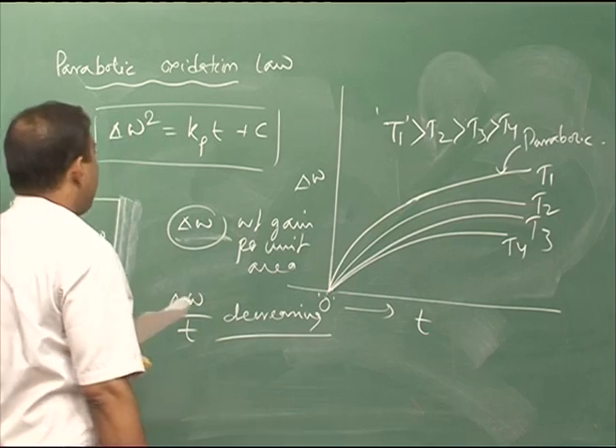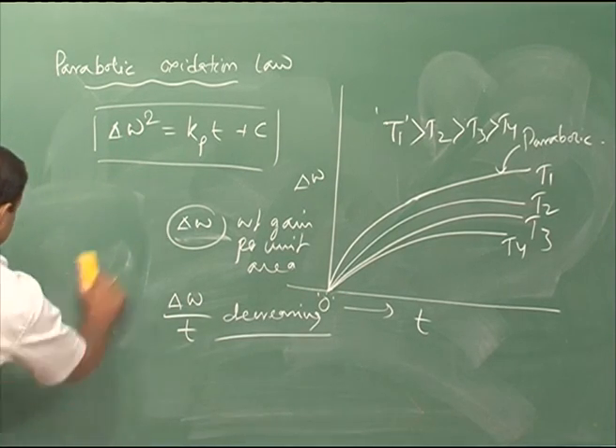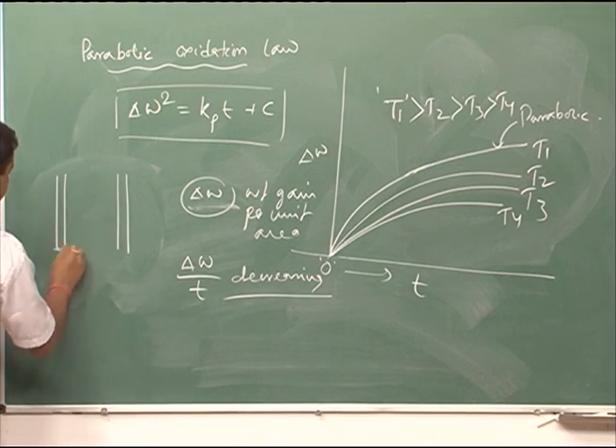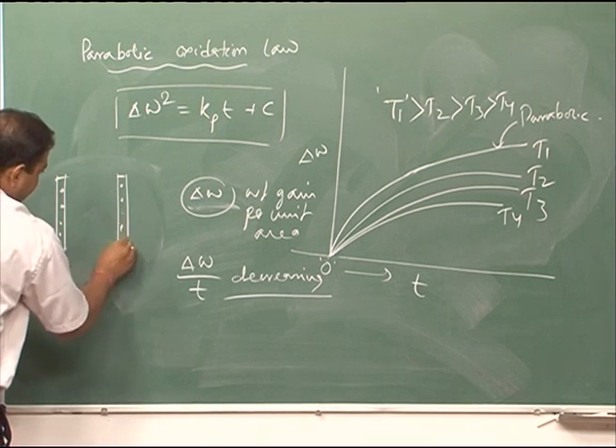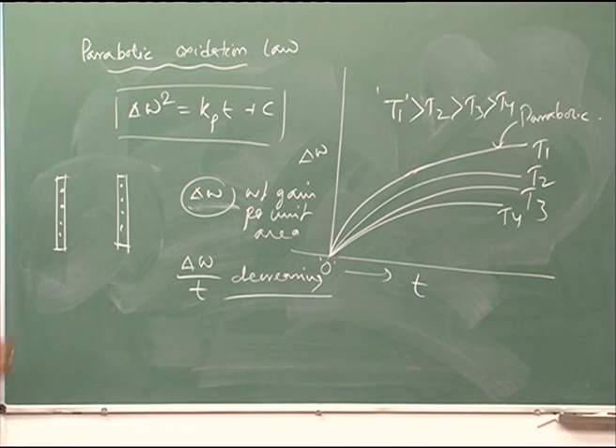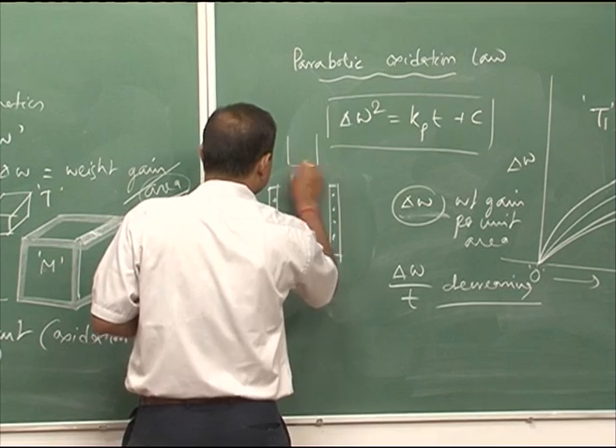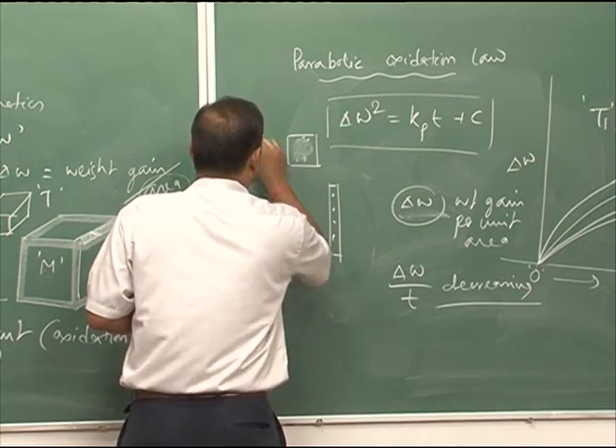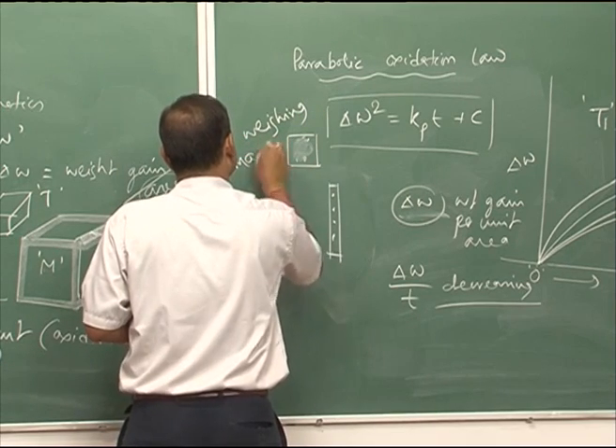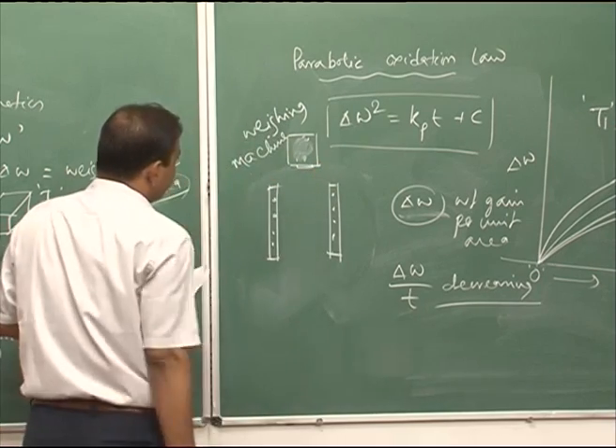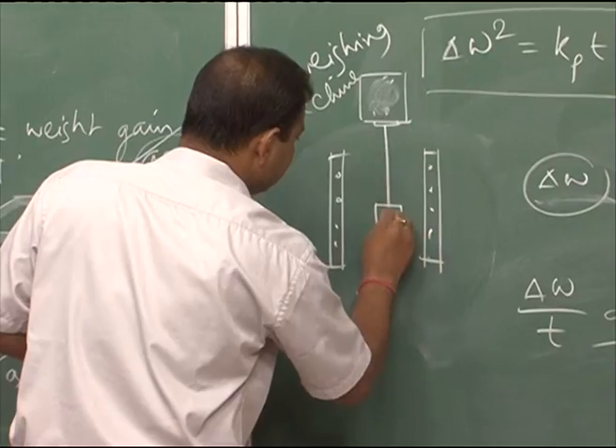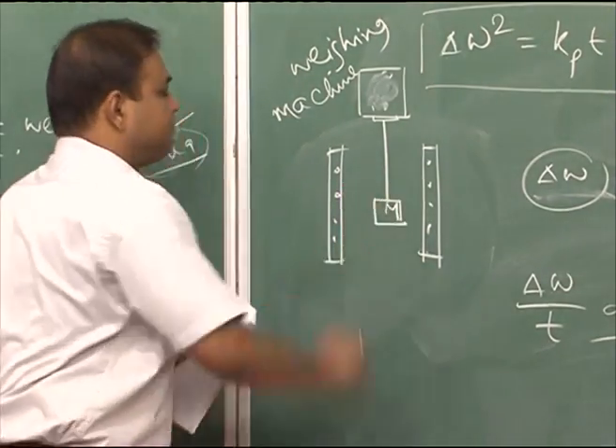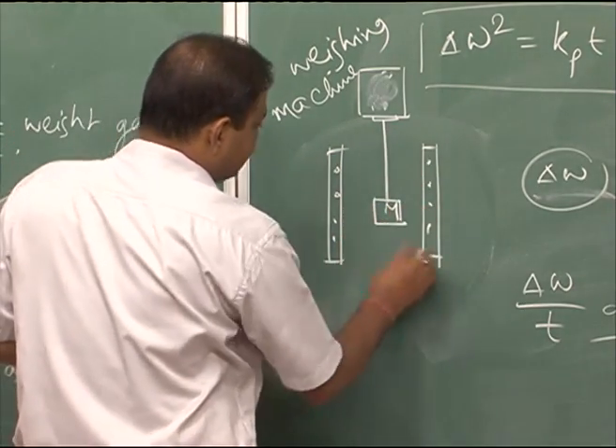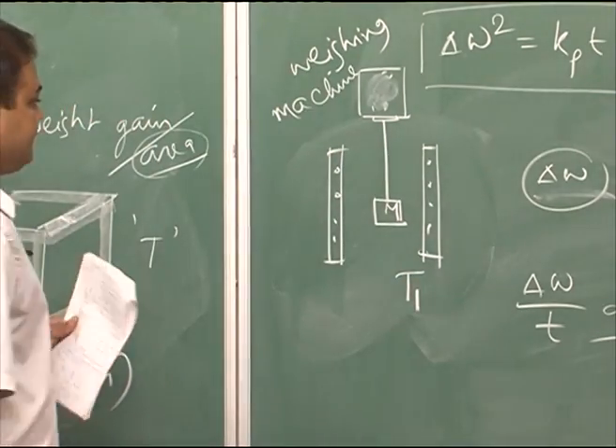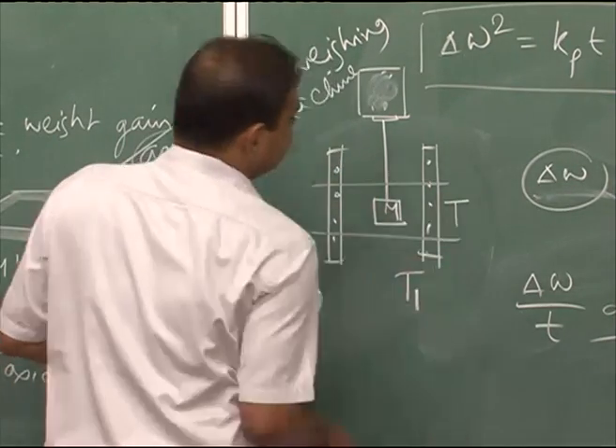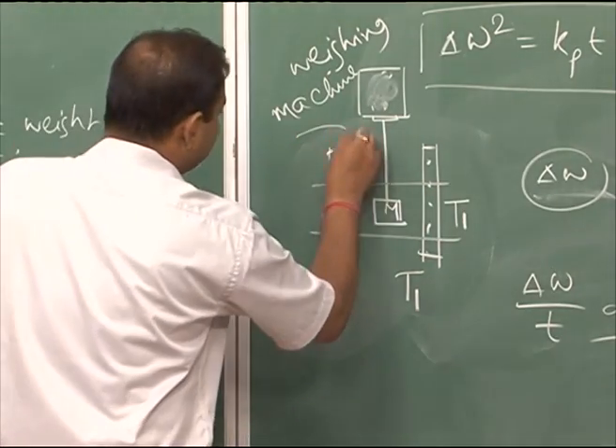How do we do that? Let us say I have one furnace, a vertical furnace, and these are my coils which heat up the furnace. Now, you have a weighing machine, this is the weighing machine WM, and here we have the bottom weighing facility, and from that I will put a sample of metal. This is my metal sample in the constant temperature zone of the furnace. Once the furnace temperature is taken to, let us say, T1, the temperature in this constant temperature zone is maintained at T1, and we can measure that with a thermocouple.